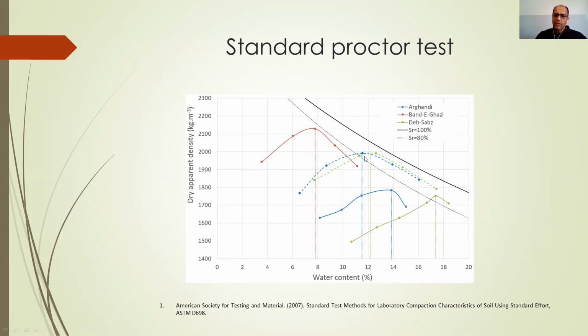This dashed blue and green line shows the reconstituted soil, because for compressed stabilized earth blocks, which we use cement, these two soils are very fine grained. There's not a lot of sand, so we used around 75% sand with this, and this is the result for the dry density.